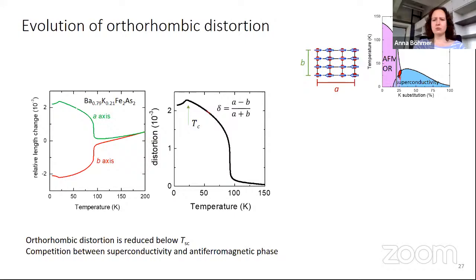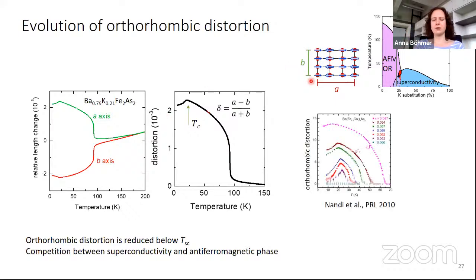When we cool down, we go through the transition, we see the orthorhombic distortion come up. We cool down further, and then we hit superconductivity, and we see the orthorhombic distortion decrease. So here's another effect of superconductivity on the structure. The fact that the electrons become superconducting, lose resistance, has a consequence that my rectangle changes shape. That was seen by other people as well. And what we conclude from this is that the superconductivity and this antiferromagnetic, striped phase, they compete. Superconductivity doesn't like the distortion, and the distortion doesn't really like superconductivity. So we learned something about the relation between these two phases.